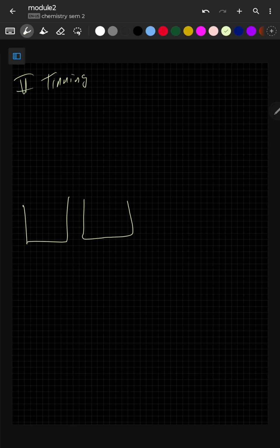Okay, now let's understand tinning. Tinning is also almost a similar process. Very few changes are there. That also let me explain now. So first the same process. First we're going to dip it in organic solvent. Then we're going to dip it in H2SO4. Then we're going to dip it in the same ZnCl2 NH4Cl buffer. Then molten tin. Then here the change is there. Palm oil. Then we're going to pass it on to rollers.